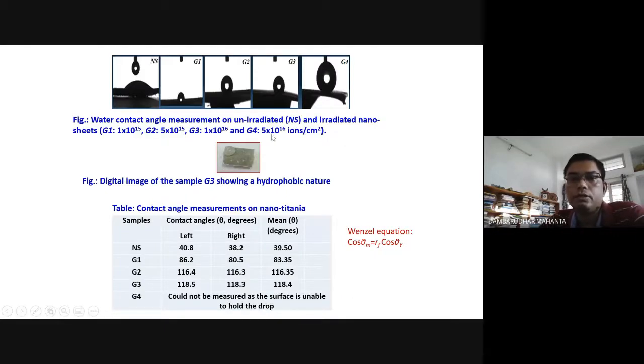All right, so these samples were measured for wettability purposes. We found that there is a drastic change from hydrophilic to hydrophobic behavior. As you could see, left, right, we have measured contact angles, and then mean degrees you could see, because of ion implantation, the surface has also become hydrophobic. So there is a transition from hydrophilicity to hydrophobic surface.